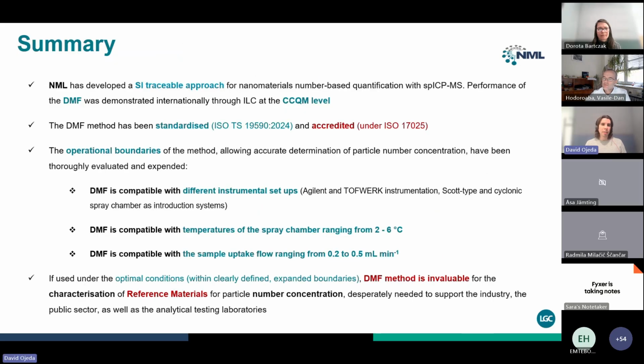So to finish the presentation, I would like to highlight again that the NML developed an SI traceable approach for nanomaterials number-based quantification with single particle ICP-MS, and the performance of this methodology, the DMF, was demonstrated through interlab comparisons at the CCQM level. The methodology was standardized under ISO documentation, and it has also been accredited really recently. Testing the operational boundaries of the method, what we saw is that the DMF is compatible with different instrumental setups, with spray chamber temperatures ranging from 2 to 6 degrees, and with sample uptake flows ranging from 0.2 to 0.5 milliliters per minute.